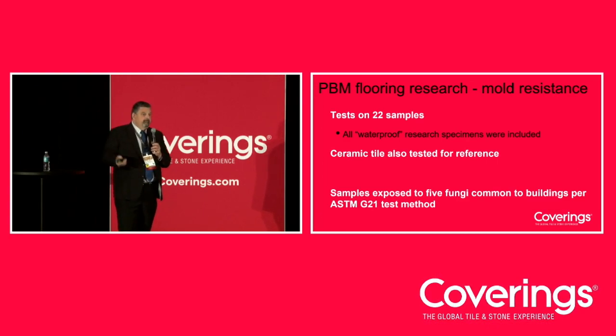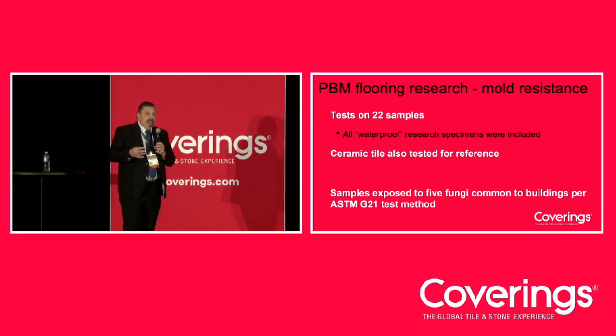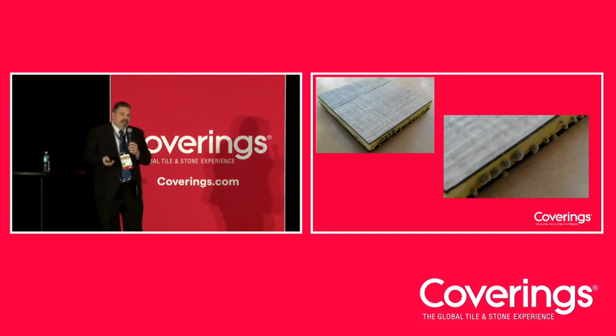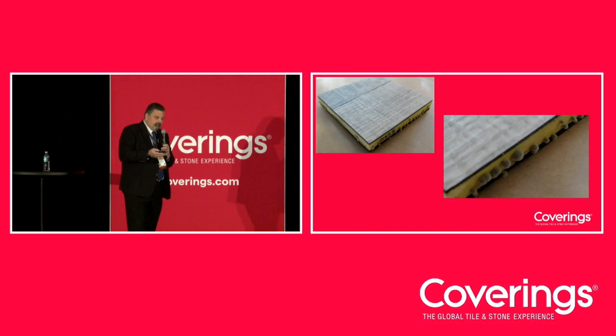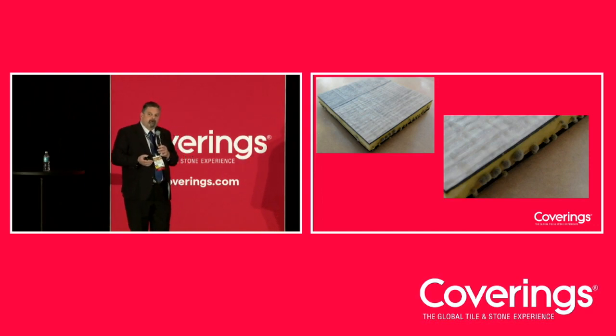So the TCNA again did 22 samples. They tested and exposed them in a standard way to 5 different types of mold. This is the picture here that I was talking about. This is mold. So all the little balls you see there, those are big chunks of mold that are growing on the side. Now, yes, it is a cut surface, but you cut this product to install it, so you're going to have these cut surfaces available.